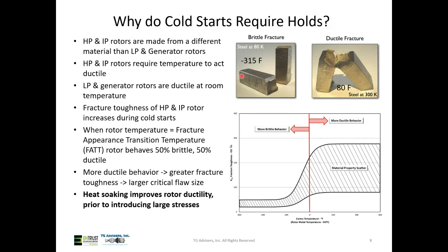is that we gotta get heat. So that's what we're showing in this plot. Essentially, you start out, this is fracture toughness. We want this number to be higher when we're cold, typically up until like 200, 300 degrees Fahrenheit. We're going to be down on this brittle type behavior. And then when we get up higher, we get improved ductility and we can withstand much larger stresses.